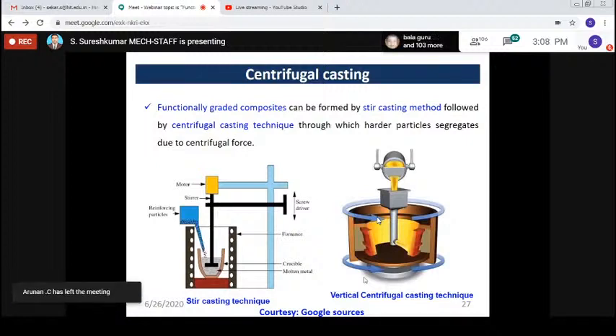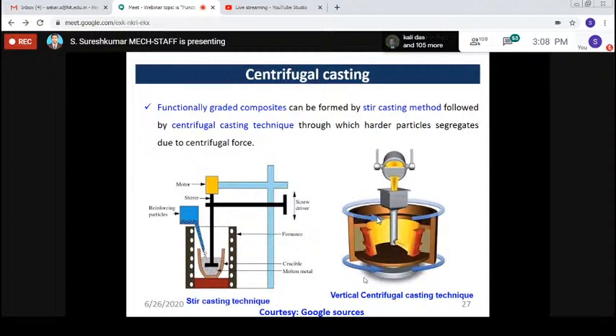Due to the swirling, rotary action, the molten metal or composite material melt is being injected, and due to the rotary motion, the material is being pulled out. While it is being poured into the die, because of the high density of the reinforcement particle, it is pulled away, whereas the lower density matrix material occupies the inner region. The outer region of the composite products has more reinforcement particles, because the ceramic reinforcement material always has higher density, higher weight or stiffness than the matrix material.